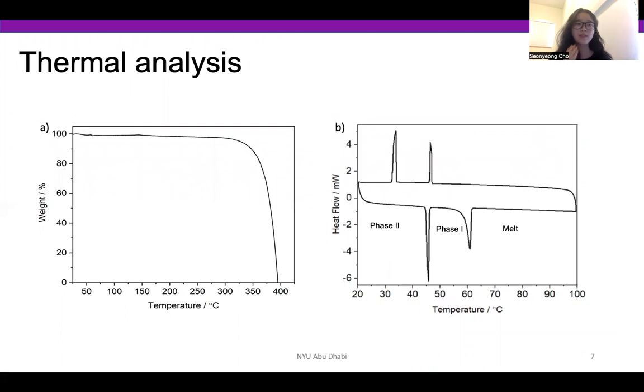First was the thermal analysis. Panel A shows the results obtained from thermogravimetric analysis. It shows that the decomposition temperature of this material is as high as 350 degrees Celsius, and it fully decomposes around 390 degrees Celsius. This is a very high decomposition temperature compared to many other OIPCs that have been reported in literature. It is also very desirable to have a high decomposition temperature and a high melting point in solid-state electrolytes because it shows that they are thermally stable. Accordingly, the DSC measurement was performed to detect the order to disorder solid-solid phase transition.